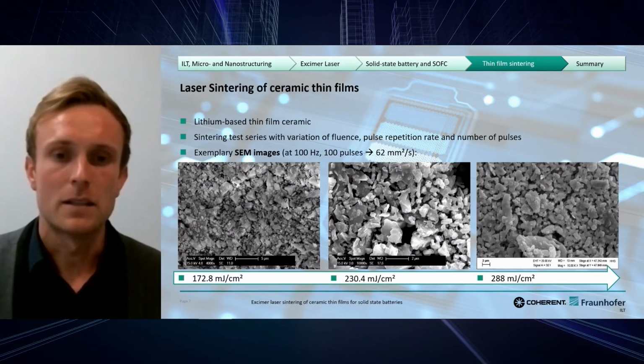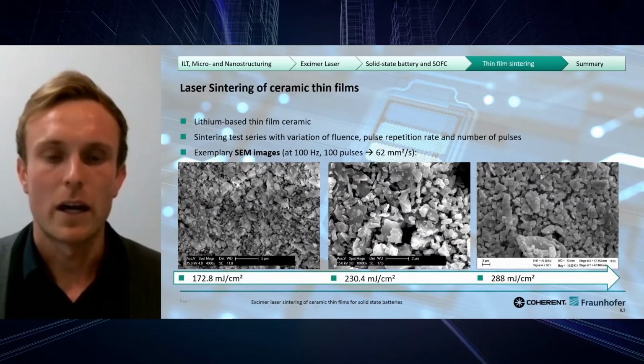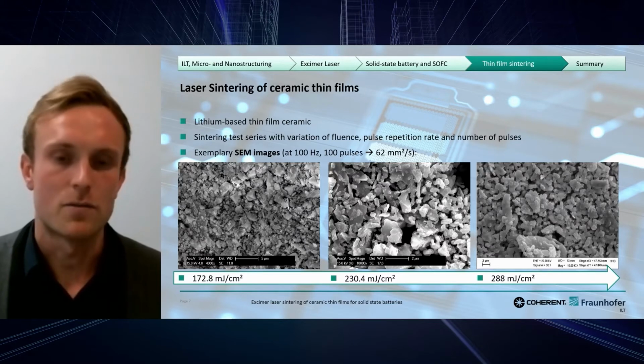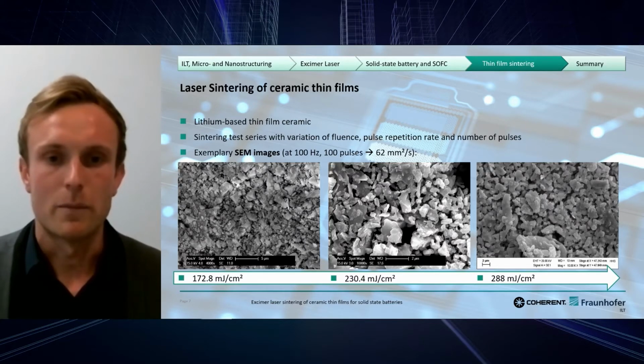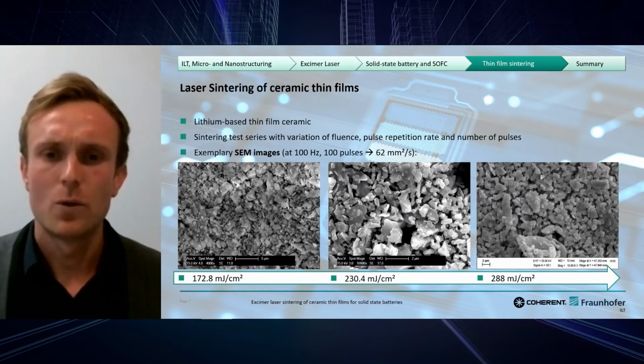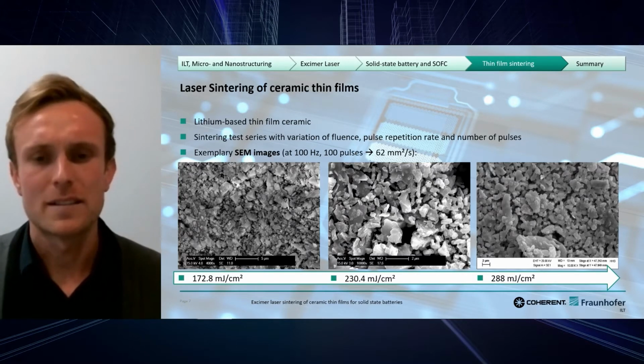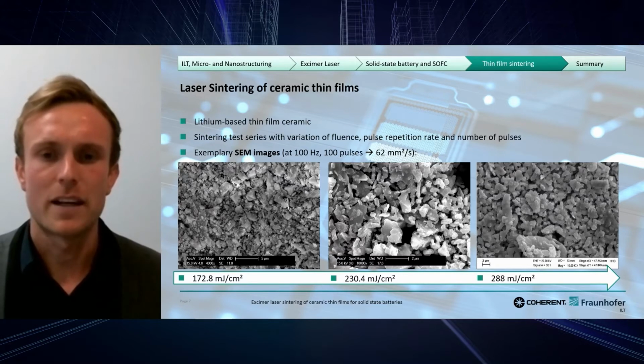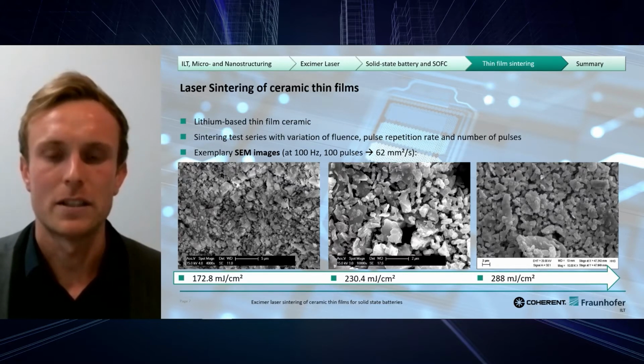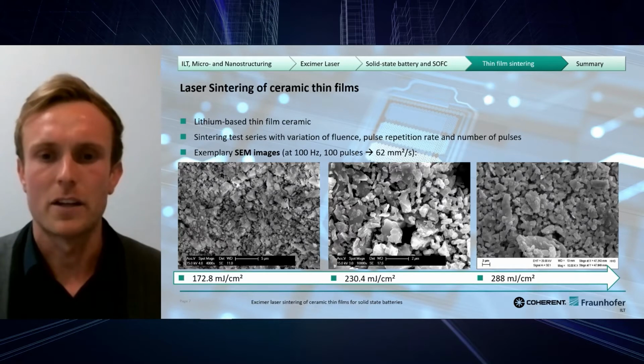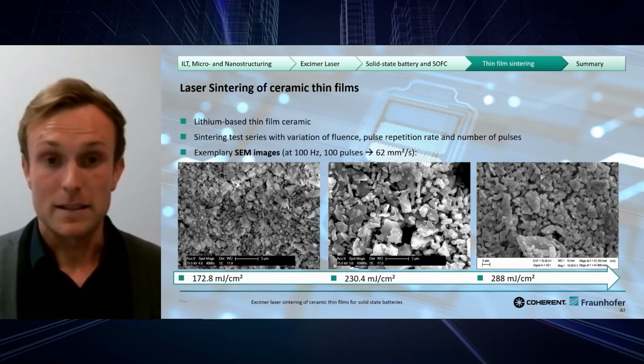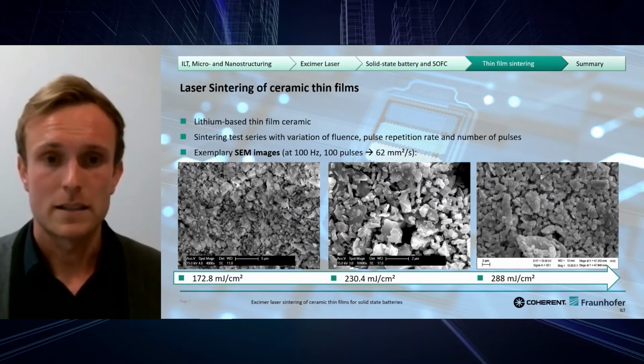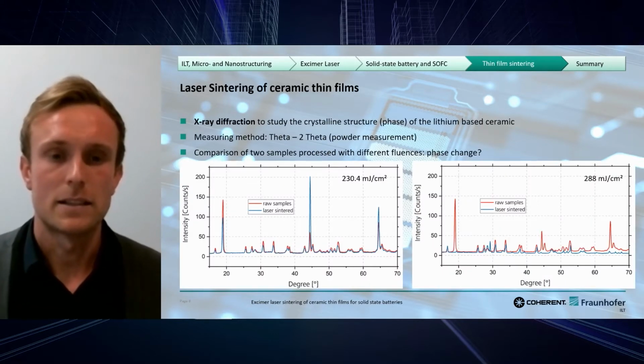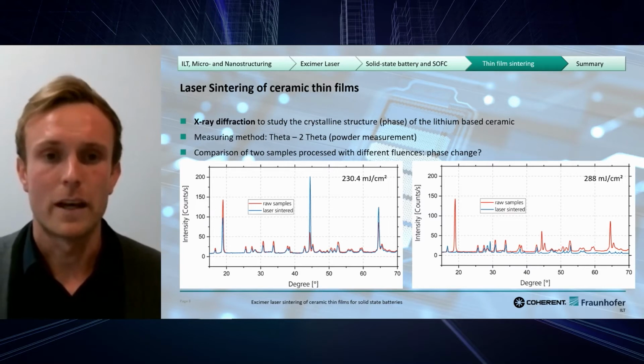In the middle, a sintering process was carried out, as can be recognized. And on the right-hand side, with the highest fluence, it's a little bit hard to interpret, but we would also say that a melting process is carried out here due to a fading of the grain structure. But sintering is possible in general. Another thing to look at is whether the electrochemical properties stay the same, or do they maintain.